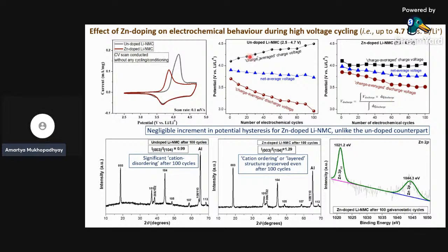Now, after 100 cycles, when we performed XRD of the cycled material, we could see that the cation disordering was significant in the case of undoped lithium NMC. This is a signature of cation mixing. A ratio less than 1.2 is considered significant; the lower the ratio of the intensity of the 003 to 104 plane, the greater the degree of cation mixing. This ratio went down from the pristine state. However, for the zinc-doped material, the ratio was almost the same as in the pristine state. So this is proof that the cation mixing could be suppressed upon zinc doping, which led to more stable electrochemical cycling.